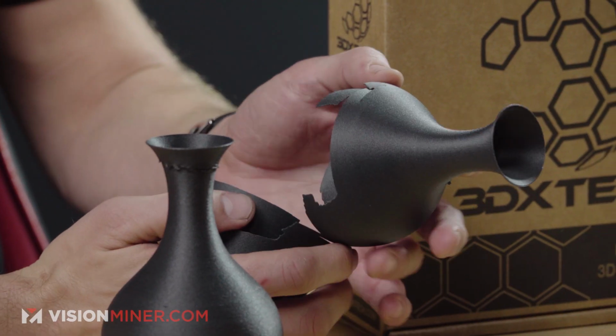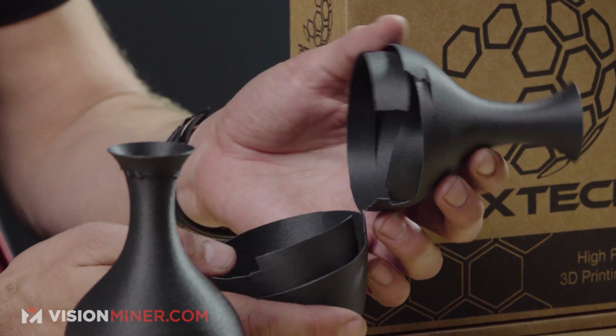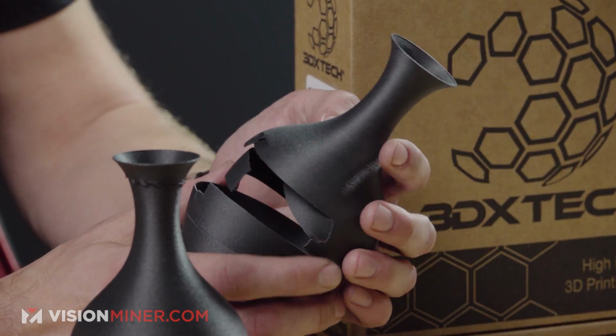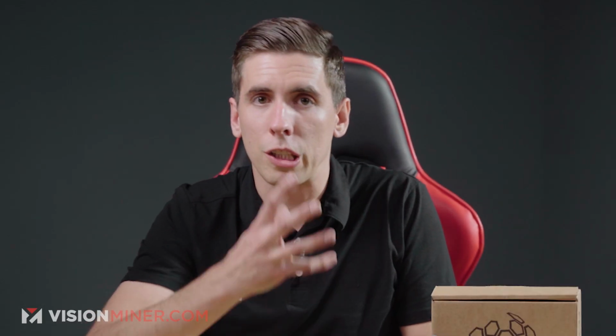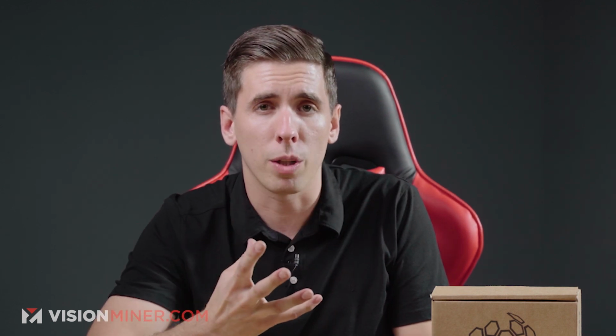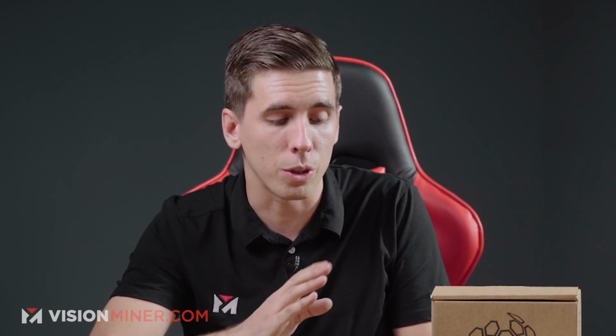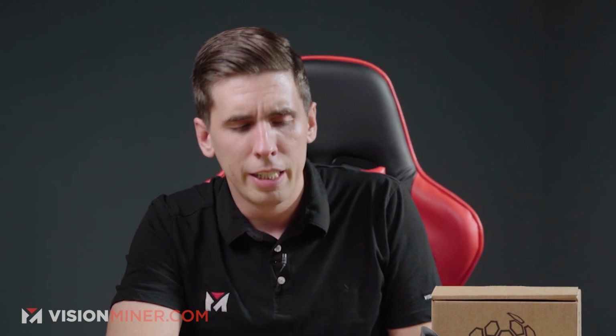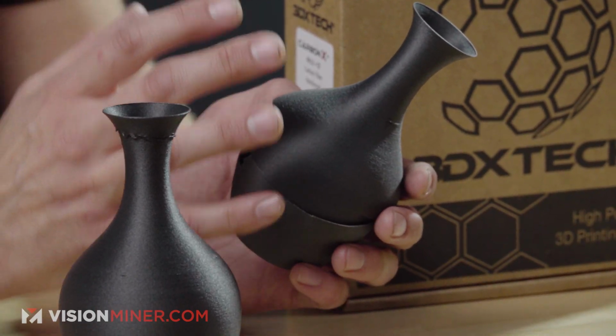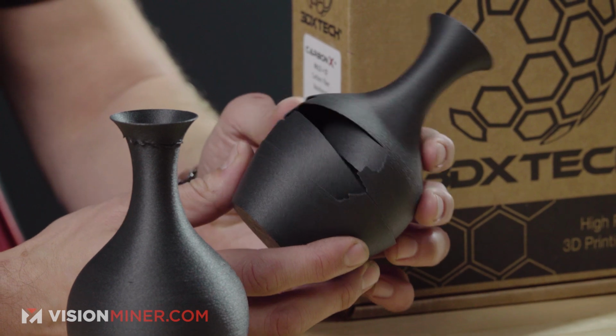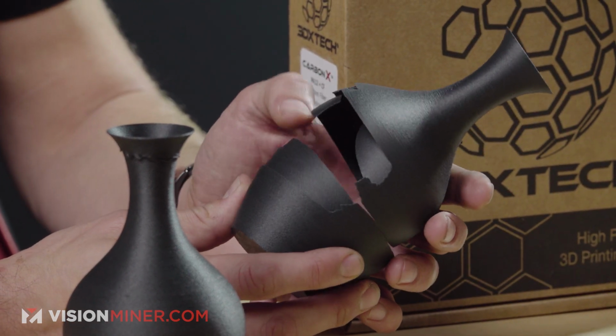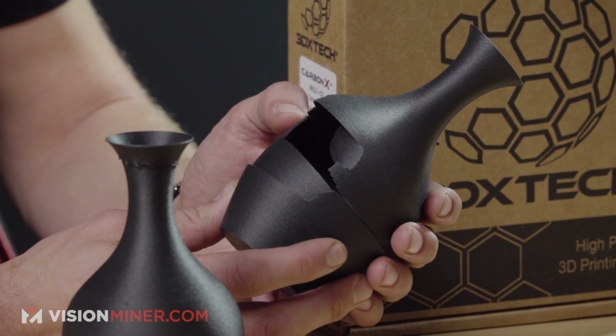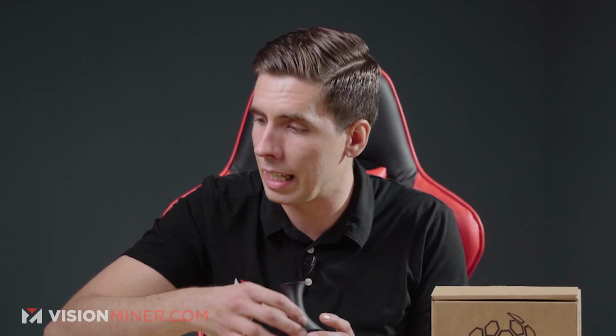As you can tell here, the surface, or the layer adhesion, wasn't quite as good as we expected. The other nylons, you can crush it and put it right back to where it was, no layer adhesion issues whatsoever. But this filament ended up being a little bit more brittle. As you can see there, it broke up and down the layers, but it also did have some layer adhesion. So we changed the temperatures and printed it again.